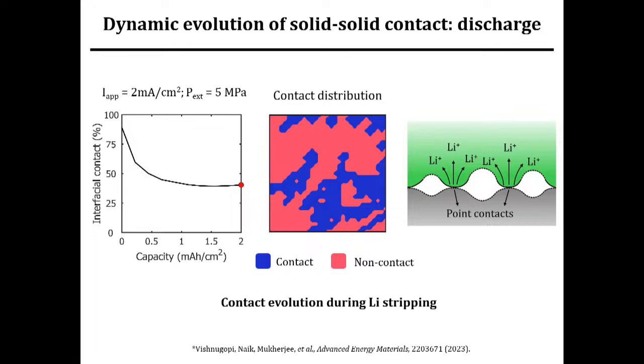A unique characteristic of solid-solid interfaces in solid-state batteries is the strong coupling that exists between their plating and stripping responses. This is mainly through the distribution and fraction of contact area that exists at the solid electrolyte and lithium metal interface. An important point to note is that design metrics such as external pressure and current density are quite asymmetric across plating and stripping, requiring us to rethink how these operational metrics are connected with the intrinsic mechanisms that happen.